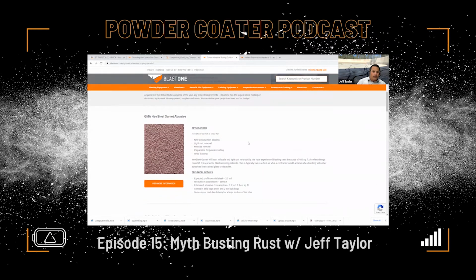If you're following along to the previous chart, it highlighted all the advantages of Garnet, and again here we highlight some of the advantages. You're usually going to see a much faster production rate, especially on mill scale and rust. There's really no faster abrasive when it comes to mill scale than Garnet, and you see a lot of that with carbon steel and in the powder coating industry. So you're going to get a much higher production out of GMA Garnet, as well as lower consumption, and that will drive down your overall cost per square foot to blast.